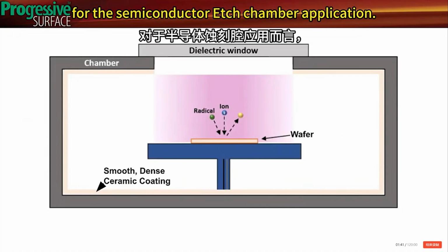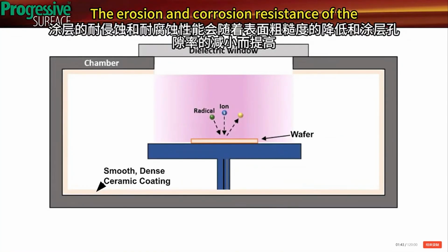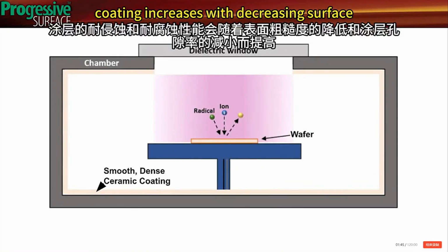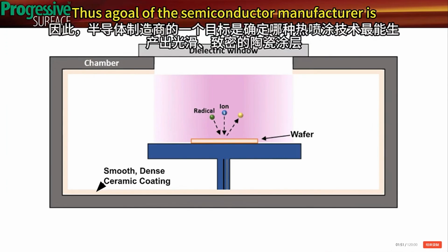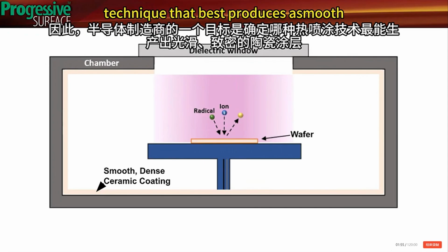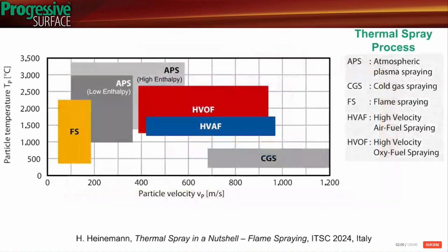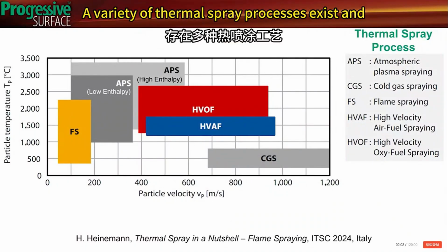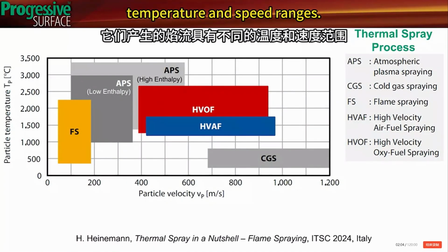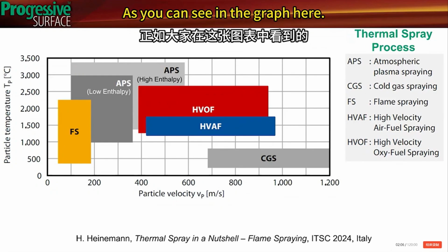For the semiconductor etch chamber application, the erosion and corrosion resistance of the coating increases with decreasing surface roughness and decreasing coating porosity. Thus, a goal of the semiconductor manufacturer is to identify the thermal spray technique that best produces a smooth, dense ceramic coating. A variety of thermal spray processes exist, and they produce plumes with different temperature and speed ranges, as you can see in the graph here.